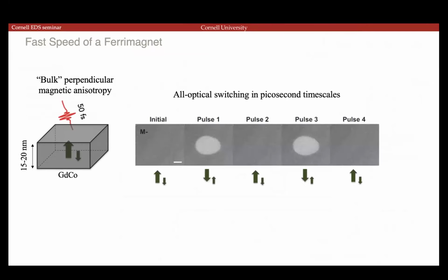During my postdoc, I had worked on gadolinium cobalt and observed that it switched ultra fast when we excite it with a laser pulse. And each of these switching behaviors, which you can see from the contrast change, happens within the picosecond time scale. What was unique though, after years of trying to understand how we grow and optimize this material, is that this ultra fast behavior and the high bandwidth only worked if the material was slightly oxidized by accident in the lab. It would only work if it was oxidized.